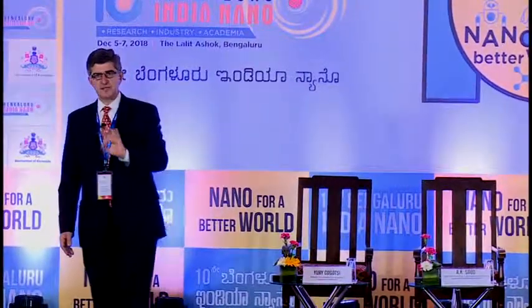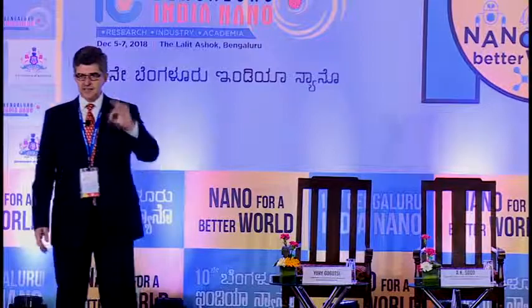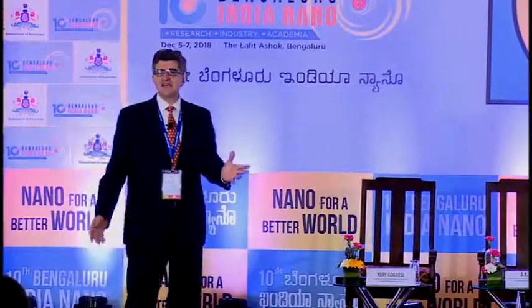Actually, the thinnest crystals that people produce now are still not a monolayer, like 2-3 nanometers, like 10 lattice parameters for moly carbide here. But a variety of other methods of synthesis are possible. So I'm pretty sure it's possible to produce a very large number of materials in a two-dimensional state and have stable 2D structures.